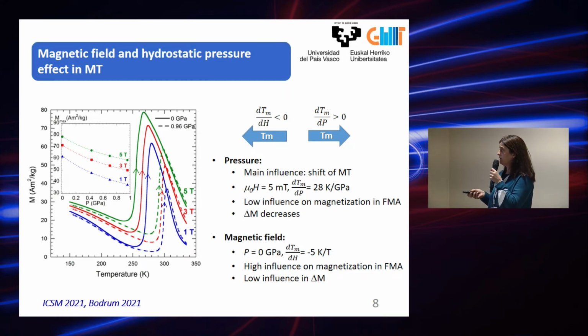The effect is opposite. It seems that the main effect is the pressure one in this, and the effect of the pressure on the magnetization seems low, but the delta M, the change of magnetization, decreases when we apply this pressure. This is because the magnetic transformation goes close to the Curie temperature, so we lose this jump. In the case of the magnetic field, there is a high influence of the magnetic field on the magnetization, but it seems that there is a low influence on the jump of the magnetic transformation.